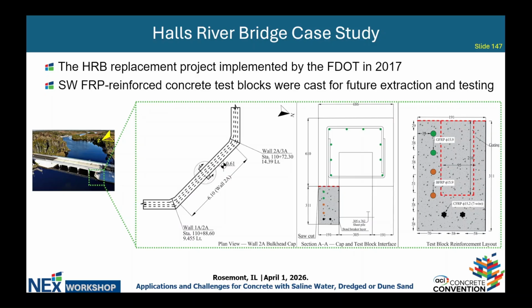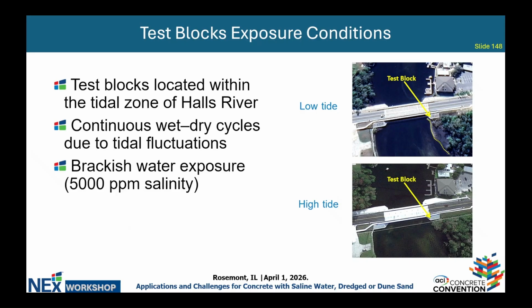The first one is seawater concrete. This test block is made with seawater, and we have FRP reinforcement, including the most conventional types: glass, basalt, and carbon fibers reinforcement, because CFRP is strand, and those two are bars. Those test blocks were exposed to real tidal fluctuations, which means that they were continuously exposed to wet and dry cycles, which is known to be one of the most aggressive concrete conditions.